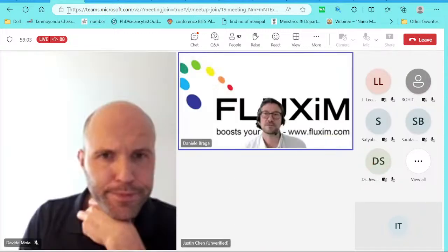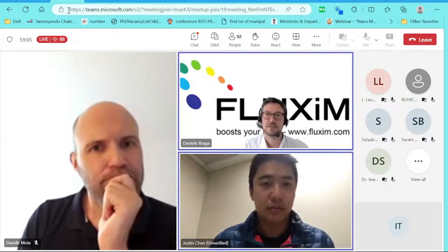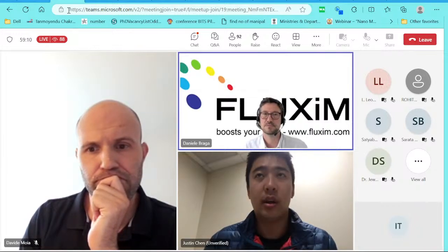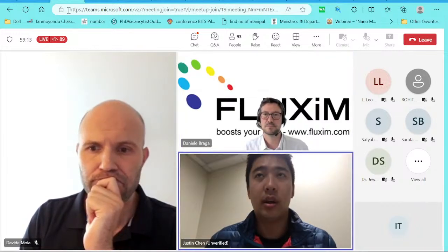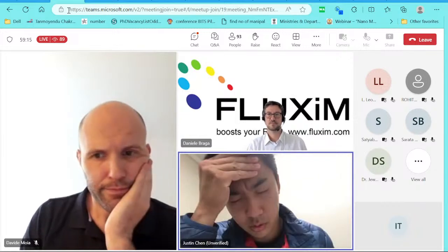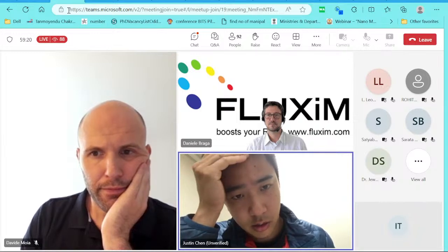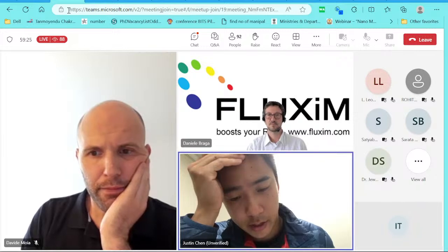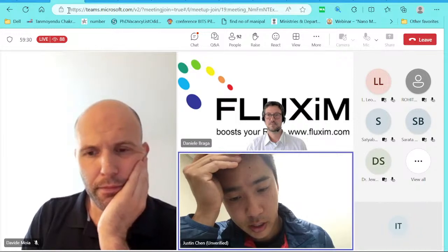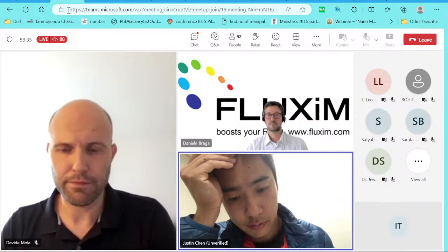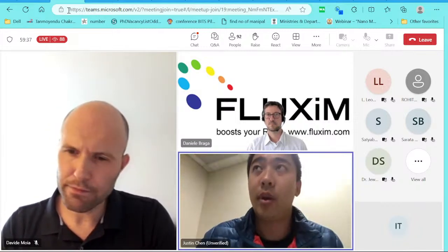Yeah, I think so. They're also asking if you could share the composition of the perovskite. Yes, we use quite a mixed one. It's by a researcher named Kai Zhu. They're based out of NREL, but it's basically like a four cation. So there's a little bit of rubidium, some cesium, some methylammonium, and formamidinium, and a little bit of bromide and iodide.